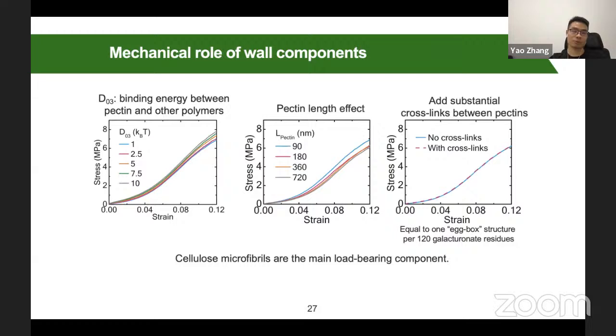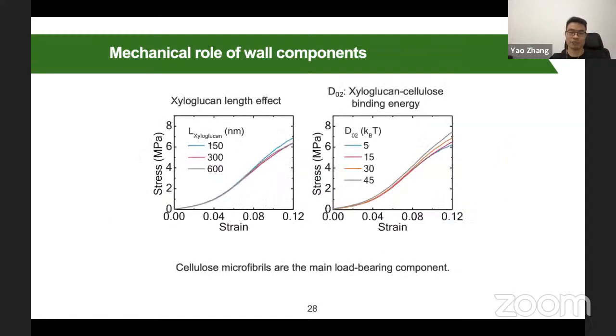And also we try to change the parameters for the other two wall components, such as the pectin length and the binding energy between pectin and other wall polymers. It doesn't generate a very large change in the stress-strain curve. And even when we add cross-links between the pectins, you can see that there's not much change with or without cross-links. The same for the xyloglucan. You can change the xyloglucan length, and also the binding energy between xyloglucan and the cellulose. It just didn't cause a profound change in the stress curve. So it all points to the cellulose microfibers being the main load bearing component.